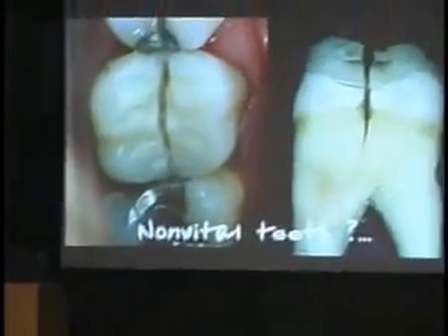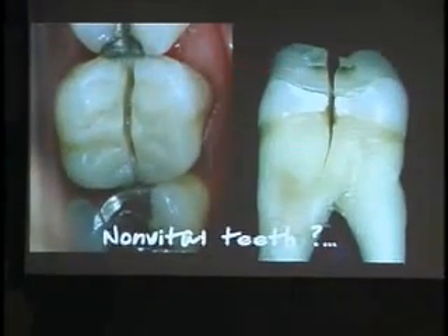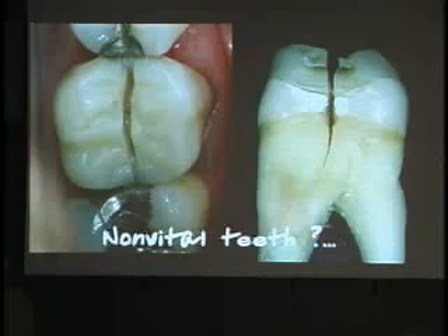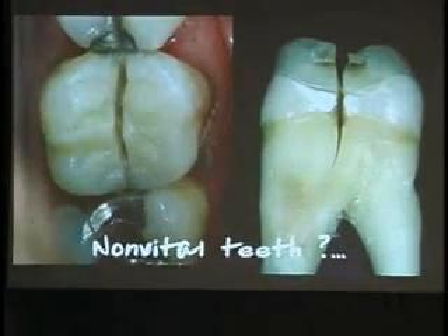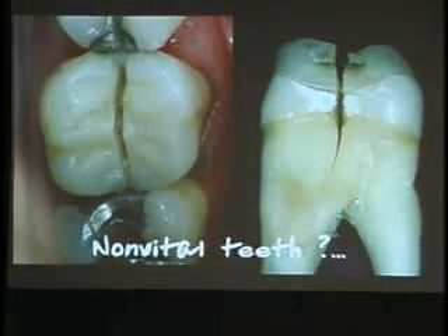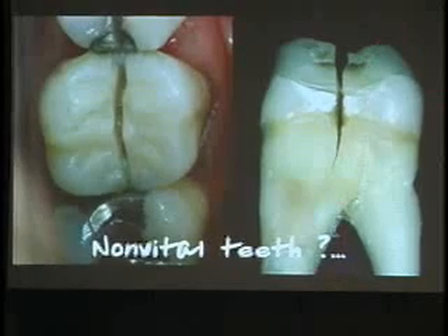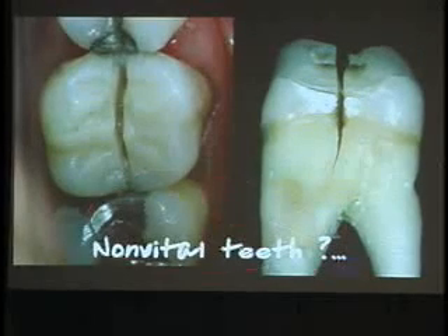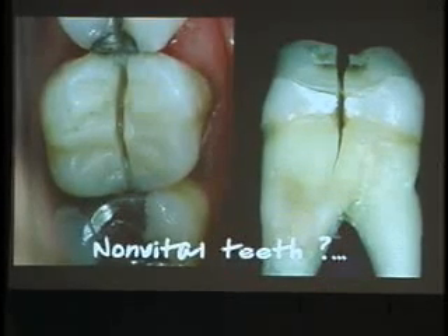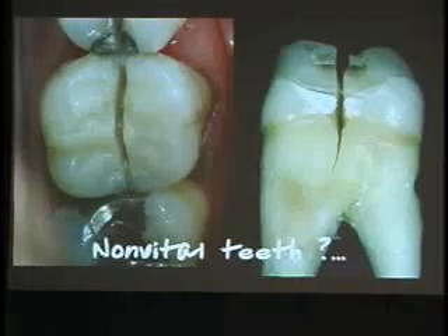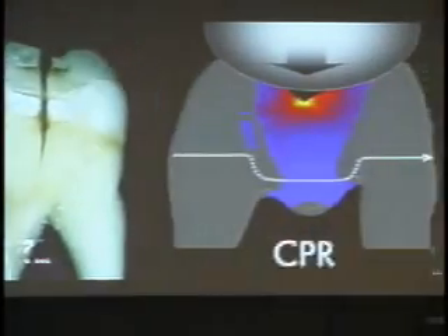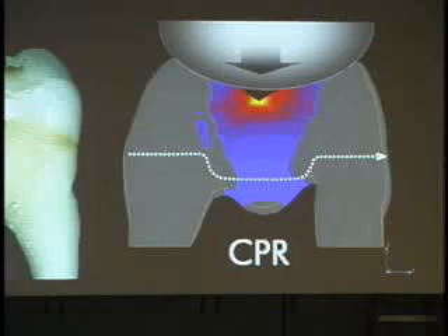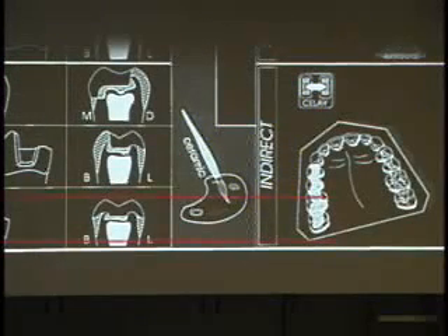Now you see this is a tooth with a complete coverage. In that case, a non-vital tooth, restored with a large composite restoration. And as I said, the protection by the cuspal coverage is here. However, when failure occurred, it was a catastrophic failure. Again, on non-vital teeth, my belief is that the cusp stabilization really needs a stiffer material, like porcelain. But again, we don't have the answers to these questions yet.